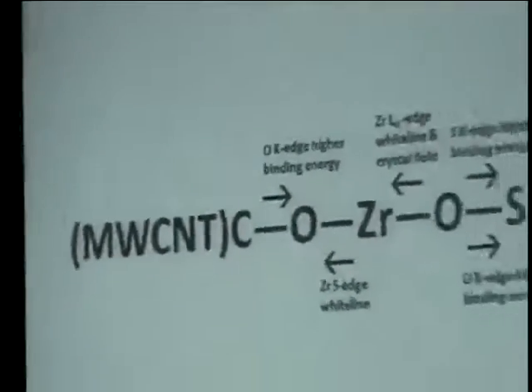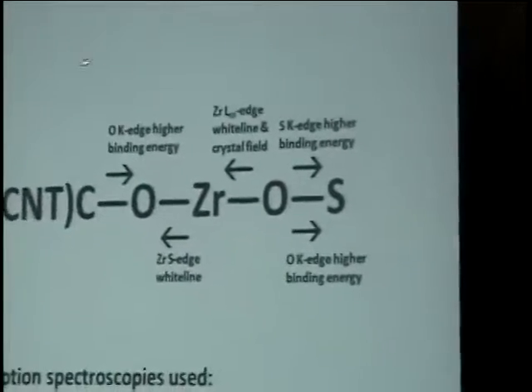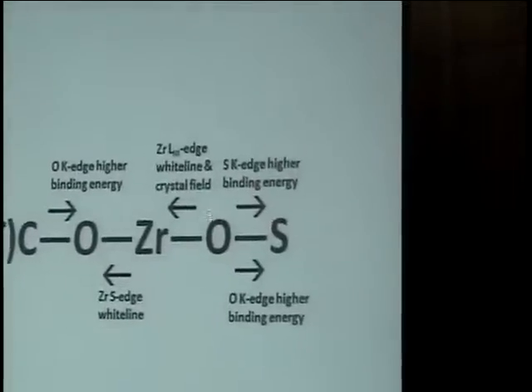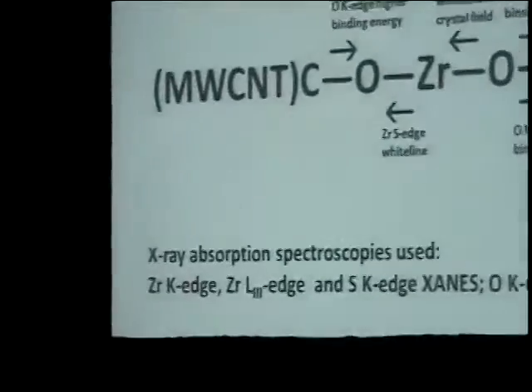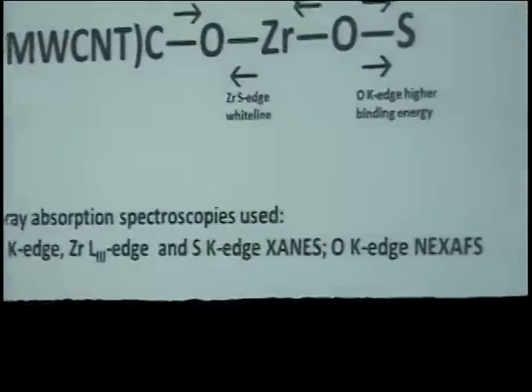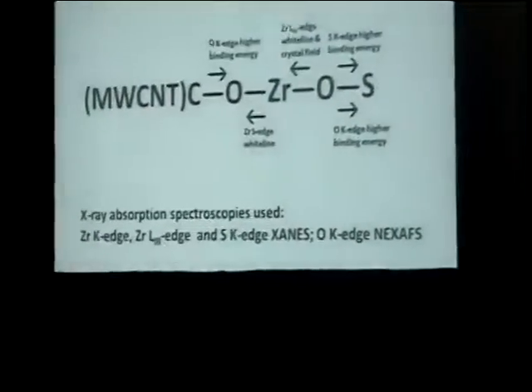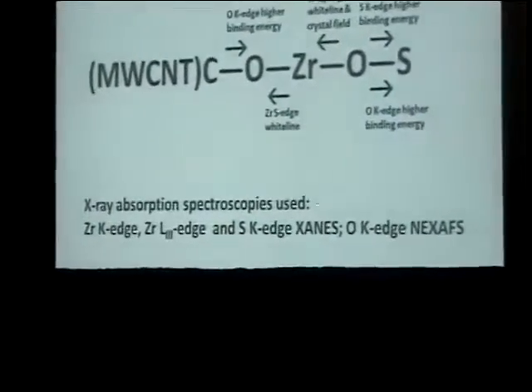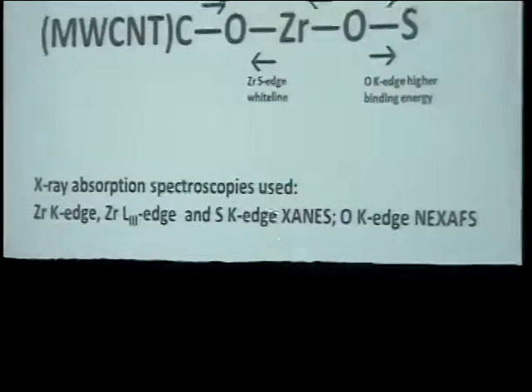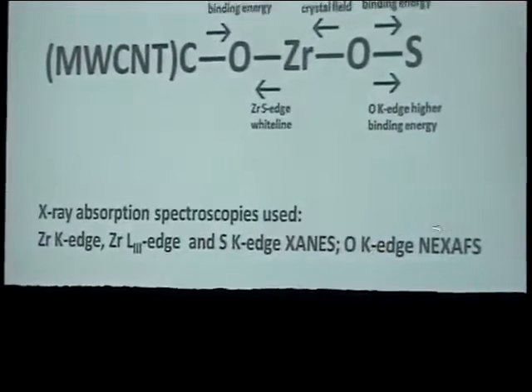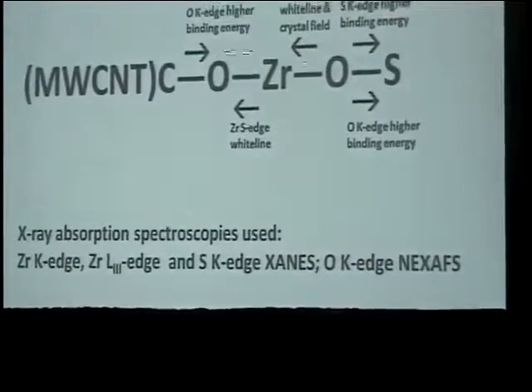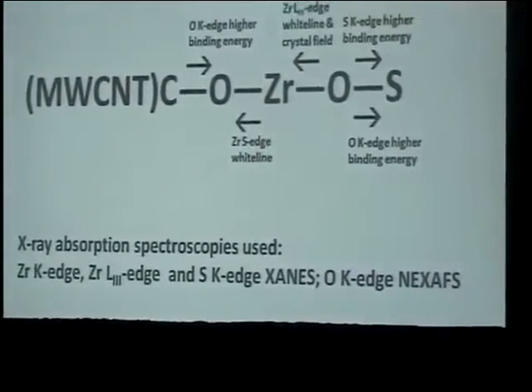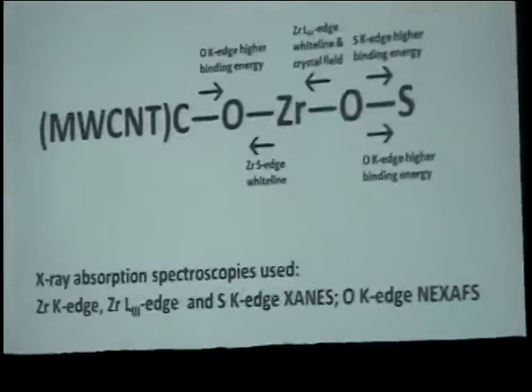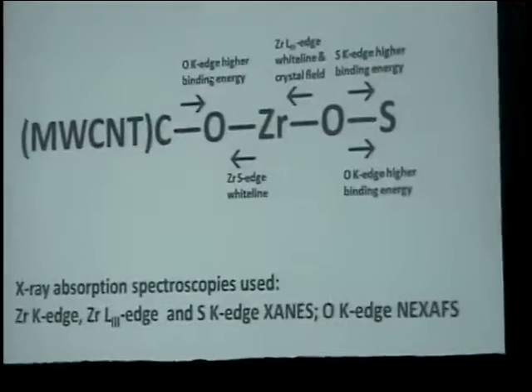So here is a whole bunch of electron transfer, which has been studied using X-ray spectroscopy. I'm not going to go through this at the moment, that's kind of the summary, but we're going to tune to the X-ray K edge of zirconium, the L3 edge of zirconium, the K edge of sulfur, and in all cases do XANES, and also we're going to do NEXAFS on the K edge of oxygen to try to deduce this flow of electrons from the different atoms in the structure, where I'm representing it simplistically.